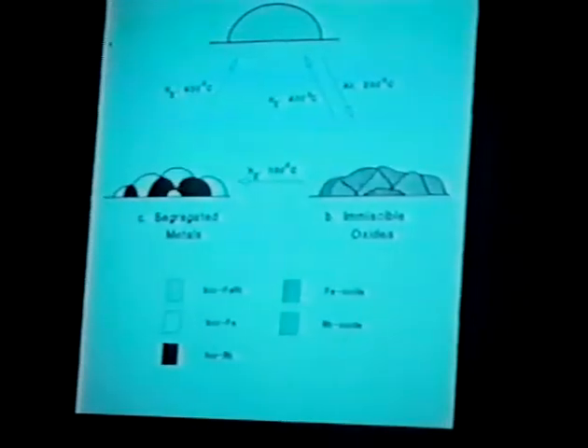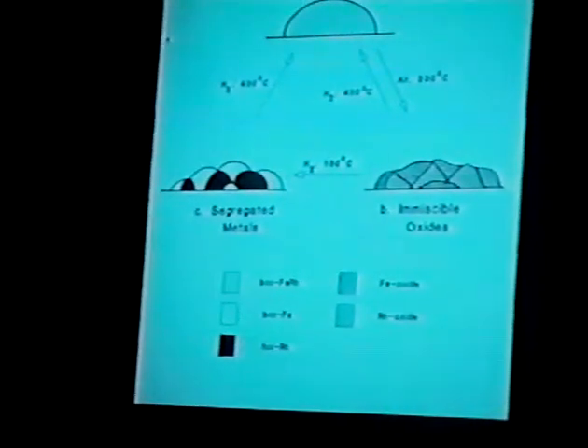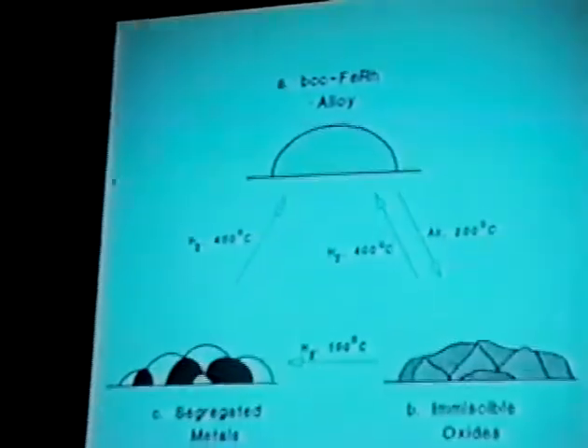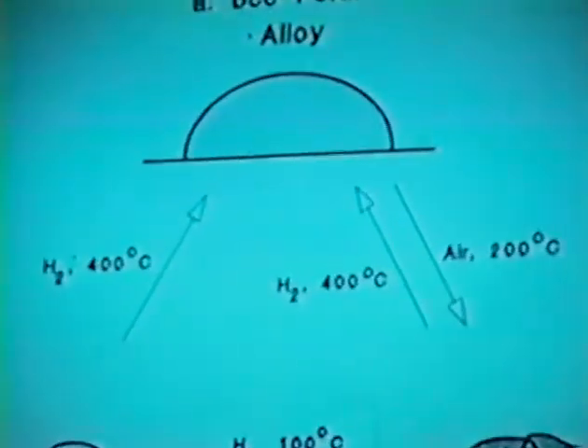And if you compare this profile with that of pure monometallic iron, they're almost overlays of one another. There tends to be a little bit of scatter, and the points tend to fall slightly below that of the monometallic extreme. But it appears as though we're adsorbing oxygen on a surface that's primarily iron. And so we think this is one model that we can use to explain the dynamics of this behavior that